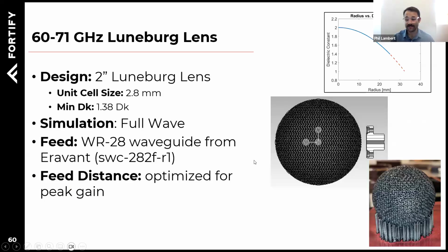Okay, Fortify is also continuing to push the limits, because as you saw in those charts where the dielectric constant range was limited up at the higher frequencies, we've done an experiment recently where we were really trying to push that to demonstrate that we can indeed manufacture lenses that operate from 60 to 71 gigahertz. And here's a 2-inch Luneburg lens design where we used a unit cell of 2.8 millimeters, so very small, with a minimum dielectric constant of that surface of 1.38.